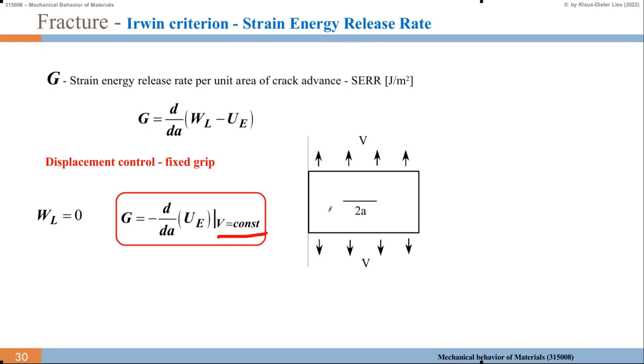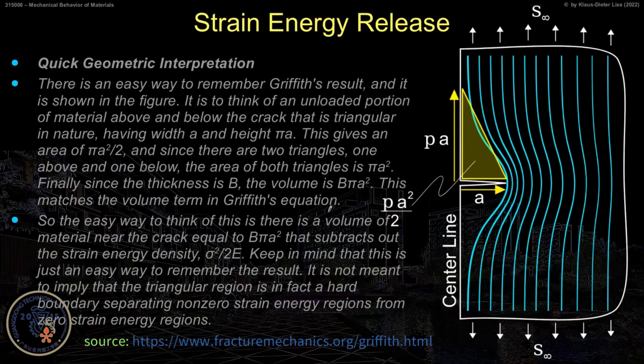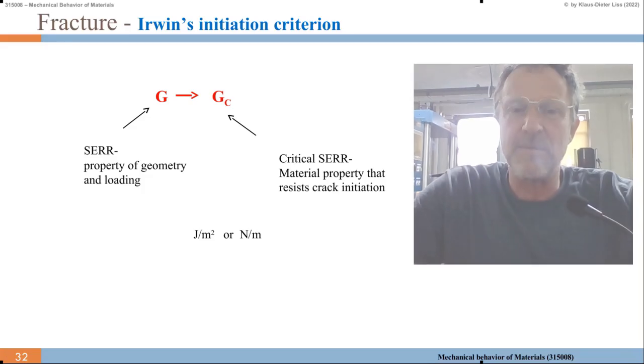So we have a pi A squared somewhere. The easy way to think of this is that there is a volume of material near the crack equal to B pi A squared that you subtract out of the strain energy density sigma squared over 2E. Keep in mind this is just an easy way to remember the result. It is not meant to imply that the triangular region is a hard boundary separating non-zero strain energy regions from zero strain energy regions. These are continuous variables, continuous fields, as we know.